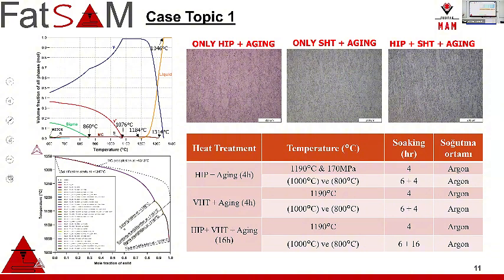When you do heat treatments, you have two things, as I said before, recovery, recrystallization, and cooling down. So in each case, it can be either solid solution strengthening or precipitation hardening. You need heating control and cooling control. So for the final grain size, depending on the diffusion rate, segregated alloying elements in the desired microstructures, and finally, order of the grains, which we call texture. So for anisotropic structures, you need a control in the heat treatment procedure. The issue is that people misunderstand. When we call this microstructure-driven mechanical properties, what we would like to obtain is a defect-free, homogeneous ordered microstructure, and depending on the strength you want, precipitate hardened microstructure for superalloys. This is the basic explanation.